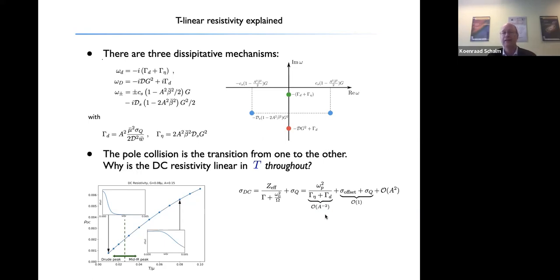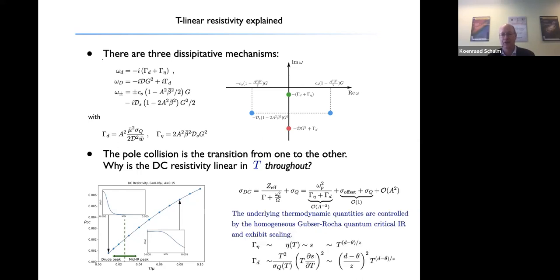How come the DC resistivity nevertheless stays linear throughout this system? Is there any reason? Because as you see, there are all these contributions in the system, and they have a very different dependence on the average chemical potential, on the charge diffusion constant. This W bar is epsilon plus P. This depends on the charge transport coefficient sigma q. This depends directly on the lattice momentum G squared. They all depend very differently on the temperature.